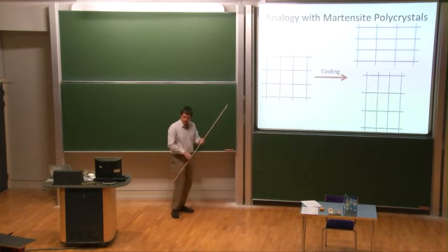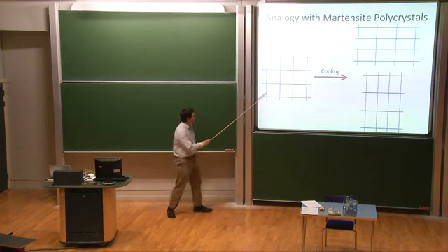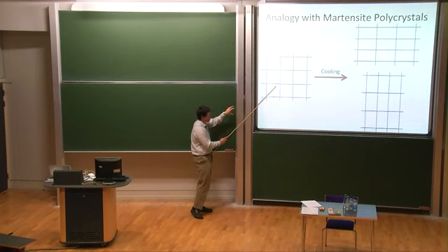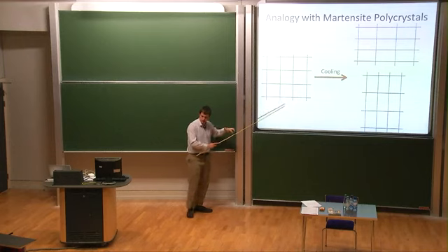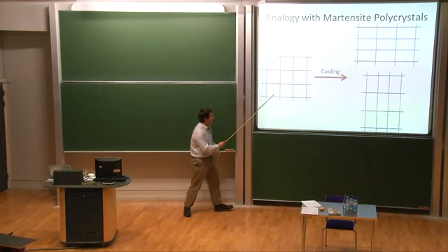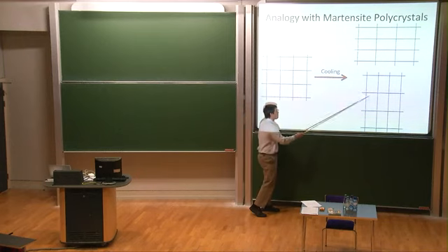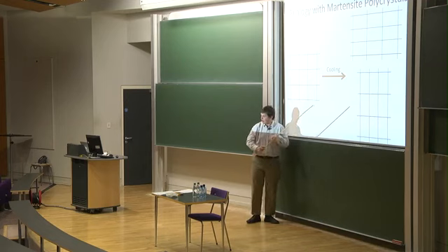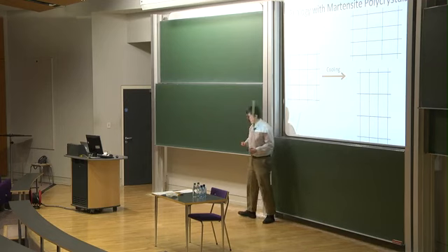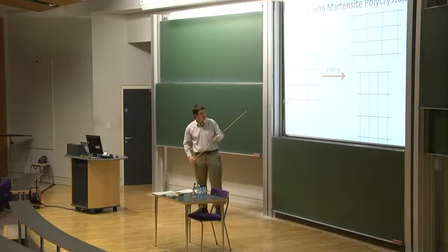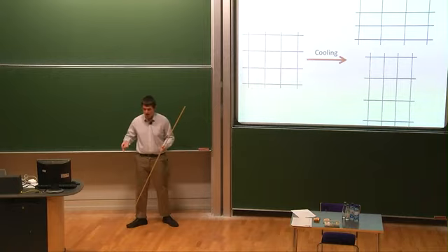So what they mean by a polycrystal is something which has a high temperature state with this high symmetry, but the symmetry is different in different places. Like the lattice has different orientations in different places. And then you cool, and you break this phase, you get the soft mode once you're already in the polycrystal state. And sometimes when you do this, you get a global soft mode, sometimes you don't.